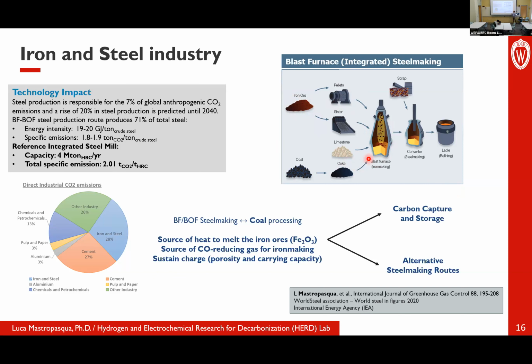And that is not just, again, as I mentioned at the beginning, to increase the temperature of the unit, but it's also a mechanical support. The coke, because it's a solid product, helps the mechanical stability of the fixed bed reactor, which is the blast furnace. So it's really hard to remove coke because it's not just a fuel source. The blast furnace produces metallic iron, and then it goes into the steel making process, which could be an electric arc furnace or a basic oxygen furnace process. So this is the way more than 70% of the steel that we produce today is produced.